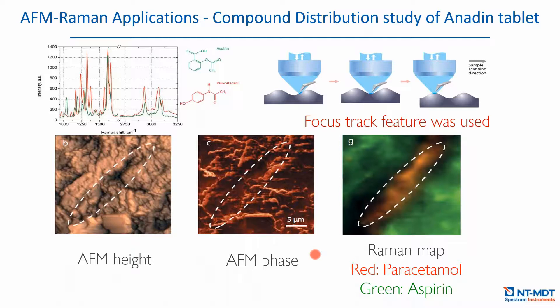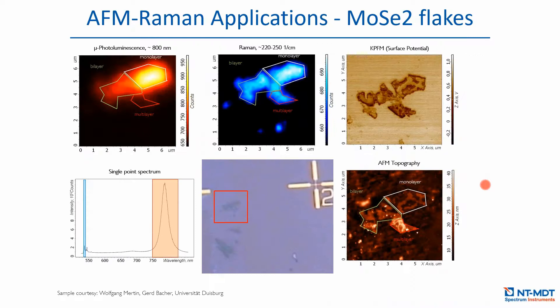Another example is the study of flakes where we can obtain photoluminescence, topography, surface potential, and Raman from the same flakes simultaneously. The optical image shows multilayer, bilayer, and monolayer regions, and we can distinguish which is which. Another important application is photocurrent mapping with localized optical excitation. One of the applications: excite the sample at a specific point with the high-resolution objective, then measure different properties like topography or run a conductivity map. In a dark room, there may be no conductivity response, but once you add the laser and excite the sample, photoconductivity appears and you can see exactly where current flows. Adding the Raman map helps distinguish what's going on with the sample.